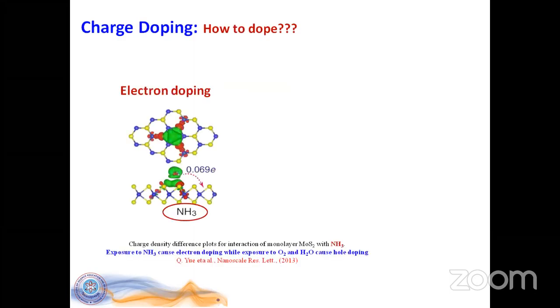Now, how do we dope? So that was the whole doping case. What if we intentionally do electron doping? Of course, one can look at gating and see how one can switch from electron doping to hole doping. Since we did not have the fabrication facility, we could not look at that. Instead, we took some simple measures. Here we exposed our flakes to ammonia vapor, and ammonia vapor is known to electron dope the system.